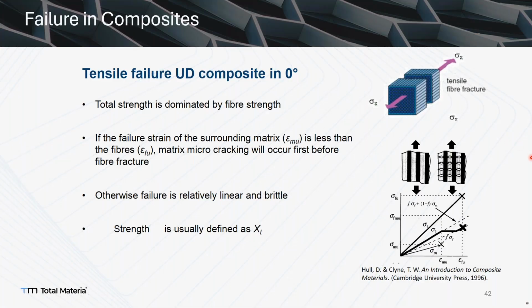Failures in composites. Right. Yeah, in this failure mode, as you can see, you have fibers in the zero direction. Most of the time for carbon fiber, you have linear and brittle fracture, but sometimes, because of the difference between the failure strains of the fibers and the matrix, it becomes nonlinear as well. Please go on. Yeah.